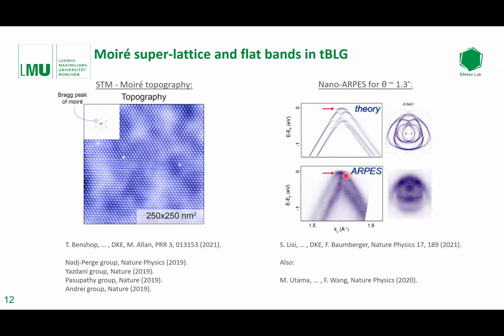Of course, things are a little bit blurred as the resolution is basically hitting the limit of what one can resolve in twisted bilayer graphene energy scales, but you can clearly see a flat band appearing close to charge neutrality. You see these energy gaps that separate it from higher order bands, and you can also see the foldings of the Fermi surface in the system.